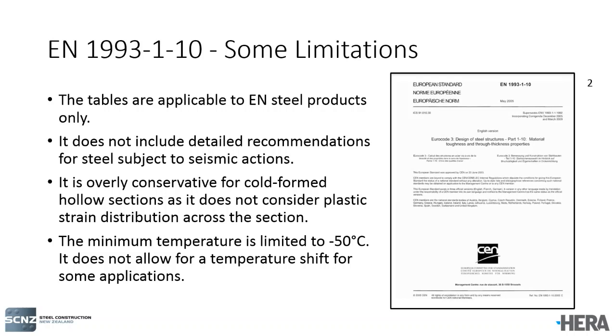And there are some new recommendations that are helping to enhance it or make it less conservative. And the minimum temperature included in the table is limited to -50. And we experience some limitations with that -50. It needs to be extended, because if you introduce temperature shift due to seismic, this actual temperature in the table needs to be lower to allow for the shift. Next slide, please.